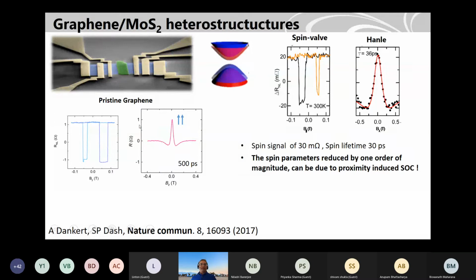So this is a comparison. This is pristine graphene, as you saw, with a large signal in ohms and a spin lifetime around 500 picoseconds, or it can be 1 nanosecond, but in this device it was like this. But when you have a heterostructure device, the spin signal is quite small, around milliohms, and the spin lifetime is 36 picoseconds here.